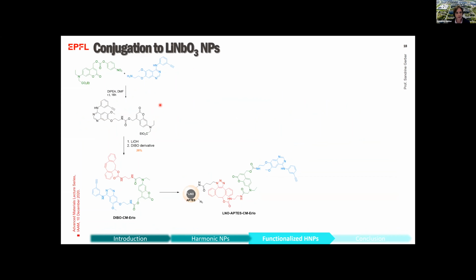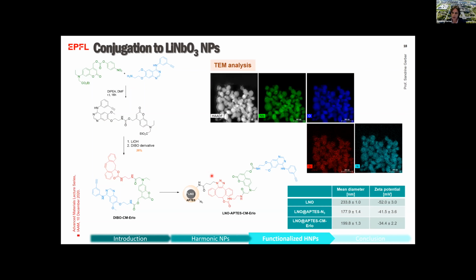So we developed a synthesis toward this analog, and then we conjugated this analog to the coumarin spacer, and finally to the activated triple bond, which gives the possibility to make the click reaction at the surface of the nanoparticles. So these are the nanoparticles that we obtained, which were characterized first by TEM, where you can see the component of the inorganic core, the silica shell, and also the functionalization. We see also the evolution of the diameter and the zeta potential during the different steps of the protocols.